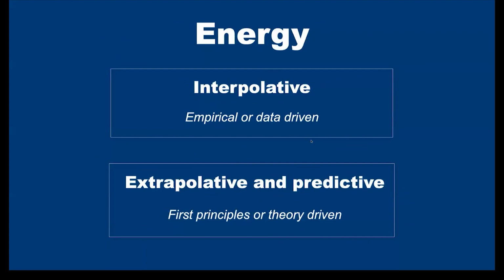Now, predicting a structure is really a global optimization problem, and structures adopt low energy configurations. So somehow you have to move the atoms around, rearrange the atoms so that they're in as low an energy arrangement as possible. Not necessarily the very lowest energy arrangement, because metastable phases are absolutely critical to biology, technology, materials science. It's not always the ground state that we're interested in, but the structures are typically fairly low on the energy landscape. So I'm using the word energy a lot, so we have to decide where we're going to get those energies from.